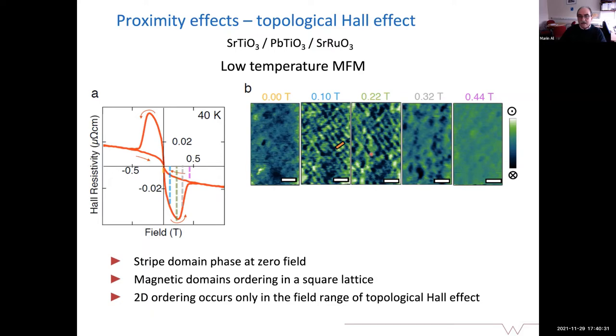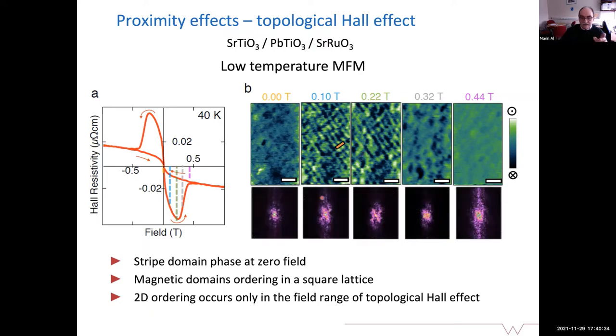And this is actually much better to see in the Fourier transform. If we Fourier transform these patterns, you see that we have 4 peaks here, which evolve with the magnetic field, and at very high magnetic fields, they disappear completely. At very, very high magnetic field, it's only one single, let's say, domain with no other magnetic structure. So it is a 2D ordering, and then we scratch our heads about what this phase would be.